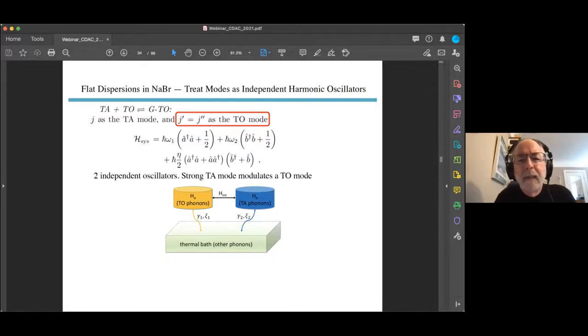Basically, you make a system Hamiltonian, which has to do with, say, the TO modes and the number of them and their frequencies, and the TA modes and the number of them. And this one modulates the other one as a product term in the Hamiltonian with a coupling parameter eta. This is a free parameter in the model. And they also include an interaction with a noise in the thermal bath down here. And the coupling to the bath and the coupling between the modes are things that need to be tuned to make this model explain the laser cavity behavior. Well, we can do that too.